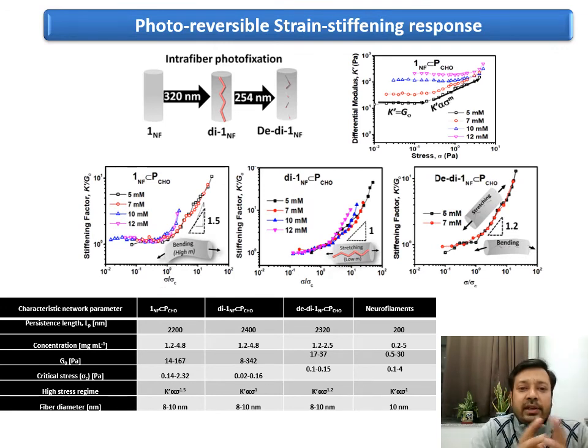Next, we wanted to understand how the intrafiber photofixation can result in a difference in the mechanism for strain stiffening. For that, we performed a differential modulus based nonlinear rheology. You can see that if you apply stress, you initially get a plateau, that is the plateau modulus, but after that it shoots up. It gives a nonlinear response, and you can quantify that by this exponent m, which is the stiffening index. For the non-photofixated sample, the photofixated sample, and also the reversibly photodefixated sample, this m value differs, and that has to do with the mode of their stiffening response. That can be either by bending of the fiber or stretching of the fiber. Most importantly, we can show that our fibers and the conjugated network show a similar response just like neurofilaments. However, our synthetic systems are even better, because these are all phototunable as compared to those other natural biopolymers.